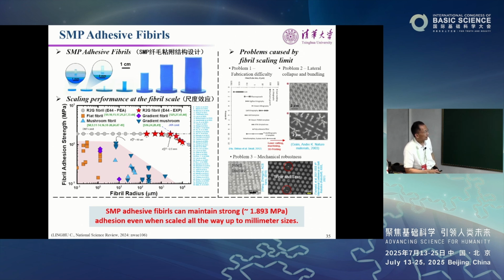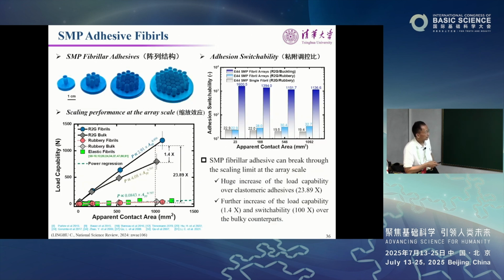Okay, so you can design these fibers. The fibers will allow you to further enhance the strength, but also design switchability. As opposed to gecko's fibers, where the hair on the gecko's feet is micrometer scale, with phase transition adhesion you can upscale it to millimeter scale, very easily fabricated. You don't need a microfabrication lab. You just make it in the laboratory. It's millimeter size, so the strength stays very high, up to millimeter scale. You can design these little fibers to enhance the controllability, to tune the switchability. We can design these kinds of arrays, and by changing the aspect ratios, we can introduce buckling and all kinds of instabilities to further tune switchability.